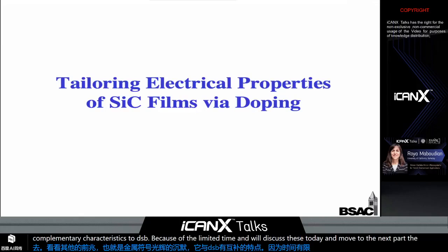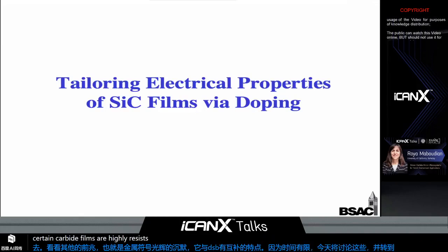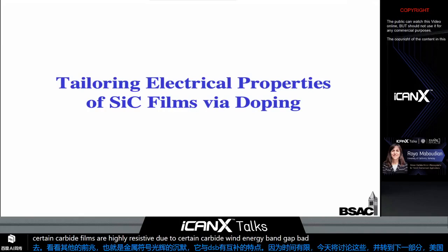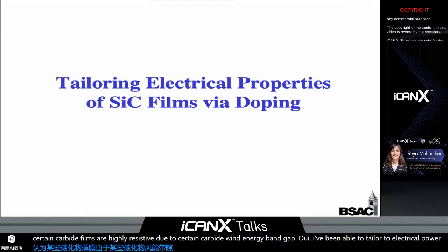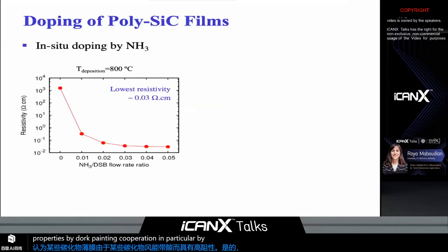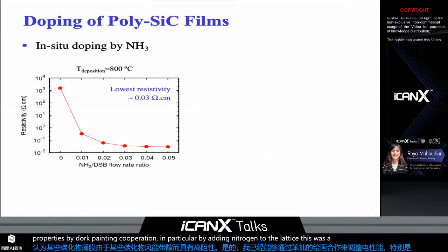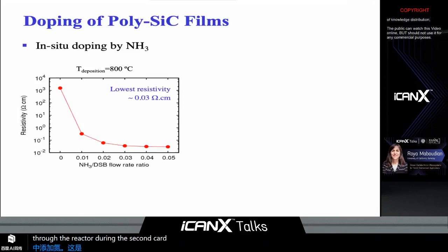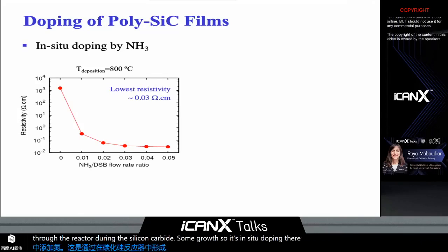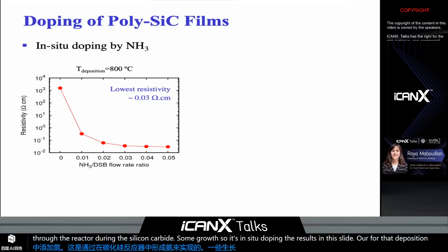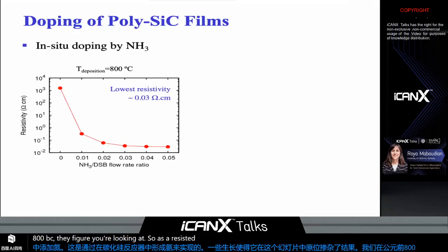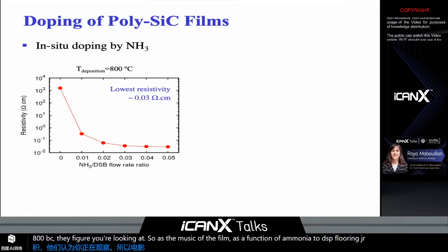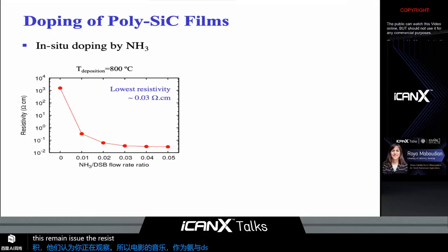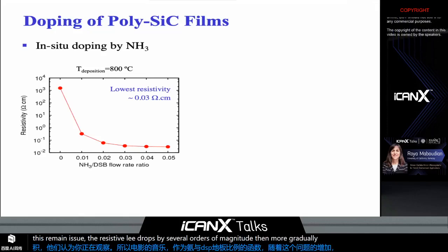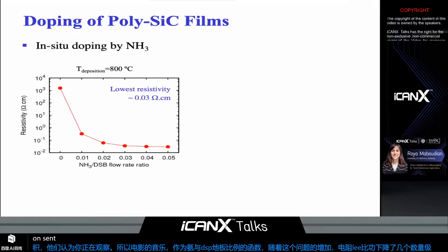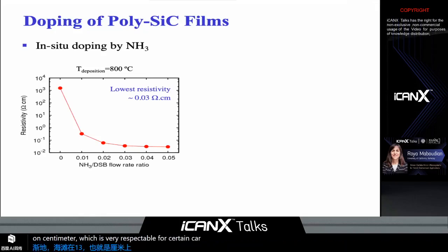The as deposited silicon carbide films are highly resistive due to silicon carbide wide energy bandgap. We have been able to tailor its electrical properties by dopant incorporation, in particular by adding nitrogen to the lattice. This was achieved by flowing ammonia through the reactor during the silicon carbide film growth, so it's in situ doping. The results in this slide are for deposition at 800 degrees C. The figure you're looking at shows the resistivity of the film as a function of ammonia to DSB flow rate ratios. With the increase in this ratio, the resistivity drops by several orders of magnitude, then more gradually reaches a plateau around 30 milliohm centimeter, which is very respectable for silicon carbide, and especially at such temperatures.